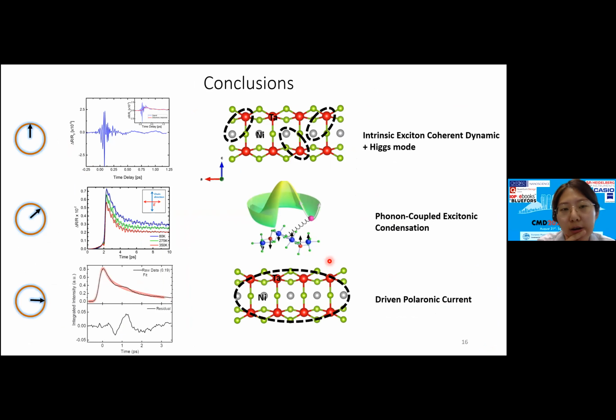Maybe if I can interrupt briefly. If you look at terahertz emission from this, if you take away the terahertz prompt, which is something we checked, you don't see any terahertz emission coming from the sample. So that would exclude any surface currents or something like this. It's really a pure transient response, not a generation response. That was double checked.